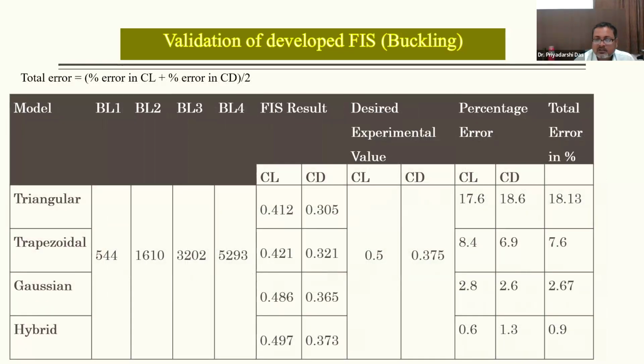Now again, when the buckling loads are provided as the input parameters, it is also validated against the experimental value. For triangular, it is 18.13. For trapezoidal, it is 7.6. There is a sharp decrease. For Gaussian, it is 2.67. The Gaussian membership function itself gives very crisp results. And for hybrid, it is 0.9. It is the closest to the experimental value. So the developed model, through experimental validation, has attained robustness, or we can say that the precision is quite high.